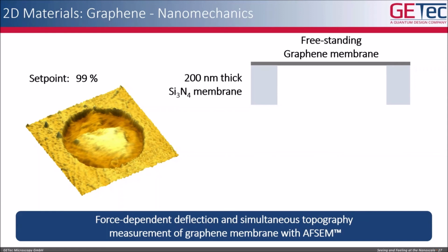There you would need set points of something like 40 or 50%, so a lot of amplitude reduction in order to get into feedback with the surface. In high vacuum, you don't have this problem of a water layer, so you can work at these extremely high set points, which really limits the interaction force between the tip and your sample.